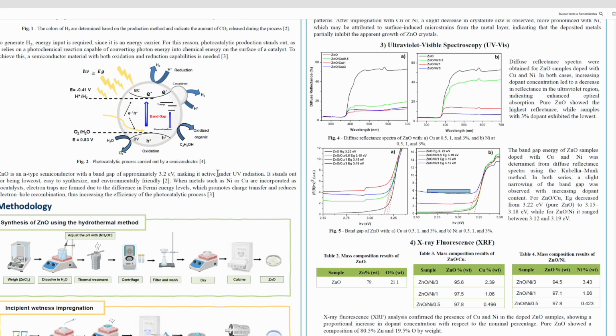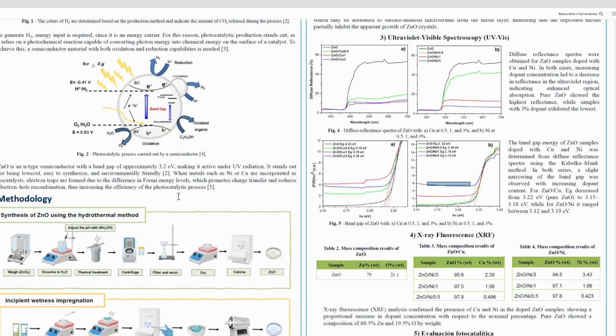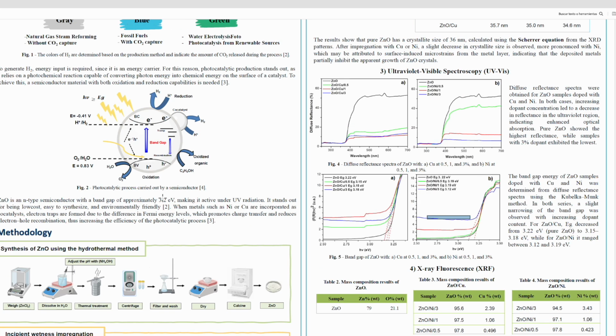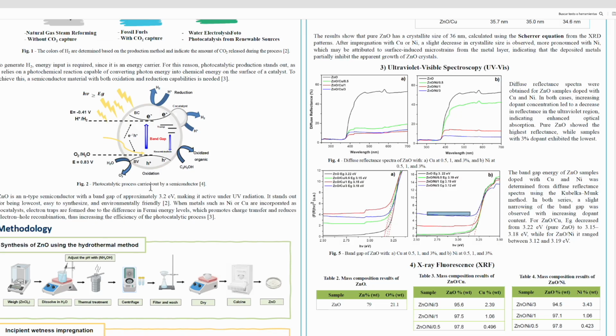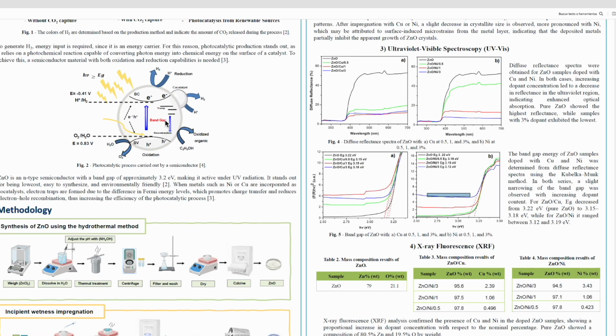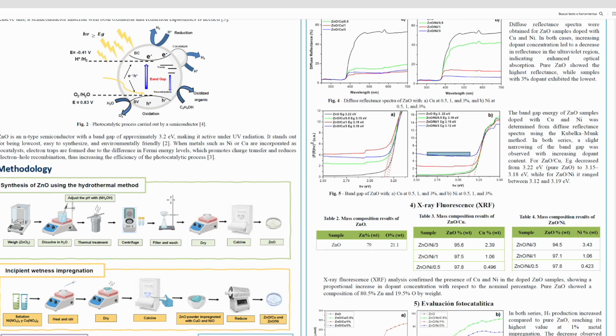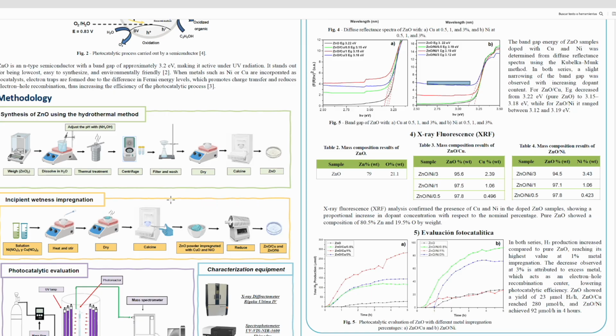What is the methodology used in this project? Well, we start by weighing our precursor, which is zinc chloride, dissolve it in water, proceed to the hydrothermal treatment, which is the autoclave part. Then we centrifuge, wash, dry, calcine, and obtain our material.